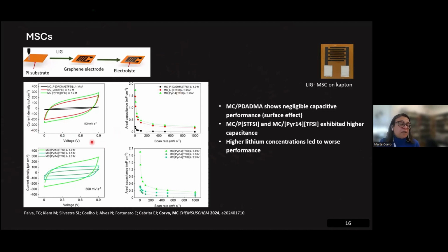Here you can see the cyclic voltammograms of these devices. As you can see, not all the gel polymer electrolytes behave the same. You have the most well-behaved ones with the methyl cellulose and the ionic liquid, the pyrrolidinium, and with the anionic polyionic liquid. These are the ones that have this square-shaped behavior that is what we are looking for. When we look at the one from the cationic polyionic liquid, this black line here, you see a negligible capacitive performance. It's only a surface effect, so it's worsening the performance.